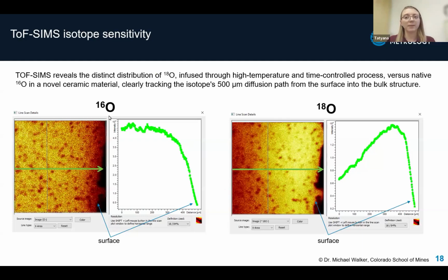In this experiment, they used ToF-SIMS to track oxygen isotope diffusion in a ceramic material. Let's break it down. On the left, you see the distribution of native oxygen isotope 16. On the right, we have oxygen 18, which was infused through the high temperature time-controlled process. So why is ToF-SIMS so powerful for this analysis?